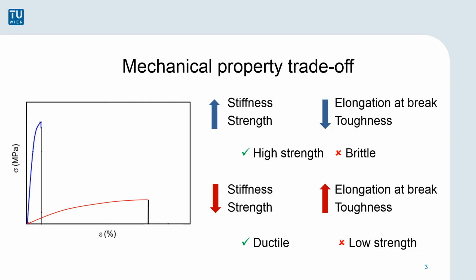Toughness refers to the energy per volume unit dissipated up to the point of fracture. Fracture toughness specifically refers to a material's ability to resist crack growth in the inevitable presence of defects. At the left side, you can see the stress-strain curve derived from an uniaxial tensile test, for example. The blue line representing a strong and stiff material, which is brittle on the other hand. The red line represents the behavior of a tough material, which is very compliant as a drawback. The ideal scenario would be a material featuring a high Young's modulus and a high tensile strength for load-bearing purposes, as well as high elongation at break for high fracture toughness.